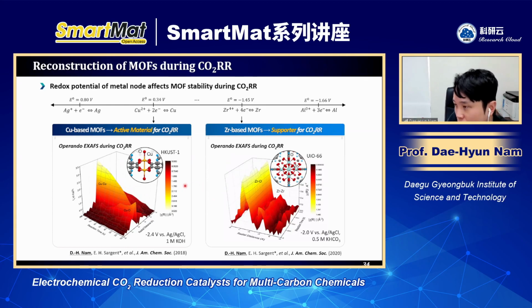What we did is that we also did some operando XAS measurements. And when we plotted the XAS, we found a very interesting phenomenon. In the case of the copper-based one, as I mentioned, it is very easy to be reduced. This graph shows the operando XAS result, this is the radial distance, and this axis shows the reaction time. This peak shows the copper-oxygen bonding. In the MOF, copper ions are coordinated by oxygen. When the reaction starts, meaning you apply the potential, this degrades, and we found the copper-copper bonding keeps increasing. It means the copper dimer in HKUST-1 is being reduced to produce copper clusters and copper nanoparticles. This shows the reconstruction of the copper-based MOF.